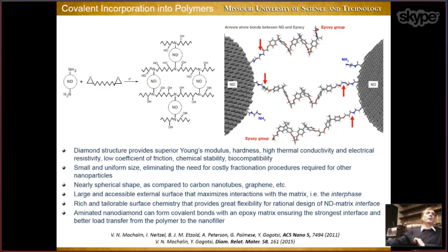So we thought that we can now replace the curing agent with our aminated nanodiamond, and basically also react it with epoxy resin. And in this case, what we expect is that nanodiamond will be covalently incorporated in the structure of this macromolecule. So by doing this, we actually get the best possible interface between the components of this so-called composite, because when you add nanoparticles into a polymer, what you produce is a composite material, a nanocomposite, right? And one of the problems in nanocomposites is that there is a very weak interface between your nanofiller, nanoparticles, and the matrix, your polymer. So when you apply mechanical load to be transferred to nanoparticles, the interface has to be very strong. Otherwise, it makes no difference.